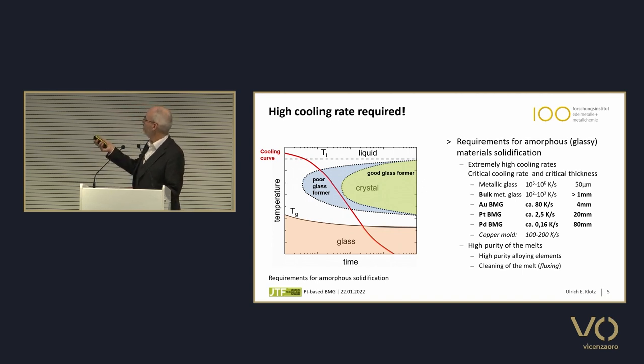And then you can only reach 50 micron thick material. But when you want to have it bulk, so massive, thicker, this has to happen at much lower cooling rates, only 100 to 1,000 Kelvin per second. And then you can reach about 1 millimeter amorphous material, and then we call it bulk metallic glass.